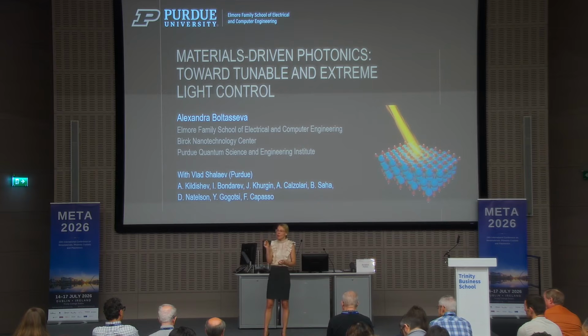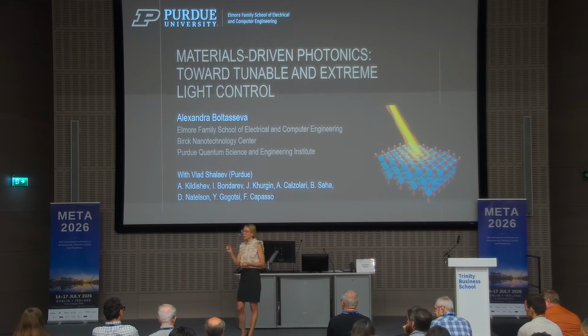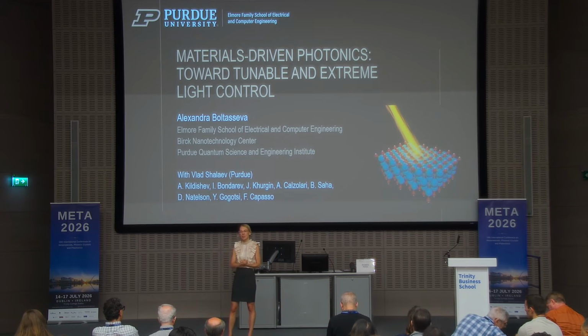You could get the actual phase diagram. Well, we do have a phase diagram. Igor has a phase diagram. The only thing we need is good quality materials and a good starting point. We have the starting point for hafnium nitride. We know that it can be seen in titanium and zirconium nitride as well for a thinner film, so maybe at a slightly lower temperature. But we have it. We have a phase diagram, and we know exactly where we have to be to be extremely sensitive to these changes, to switch between the crystallization and melted crystal stage.